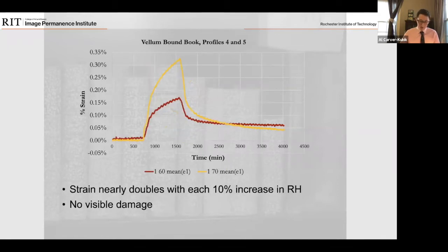Data from our absorption profiles follow a very similar pattern. As the RH increased, the objects expanded, showing positive strain. The rate slowed as the objects neared equilibrium. As the RH decreased back to 50%, objects contracted. Similar to the desorption test, the strain nearly doubled with each 10% increase in RH. So again, the red here is the profile in which we went to 60%, and this is when we went to 70%. You can see that the strain that we reached is nearly double.